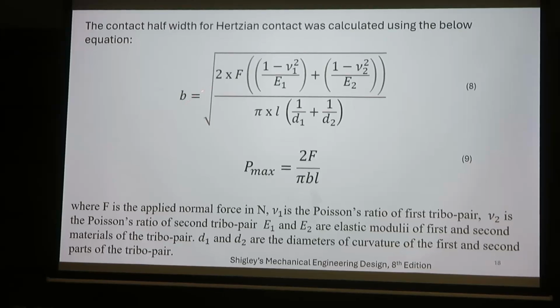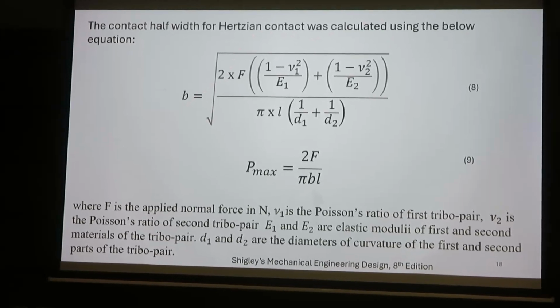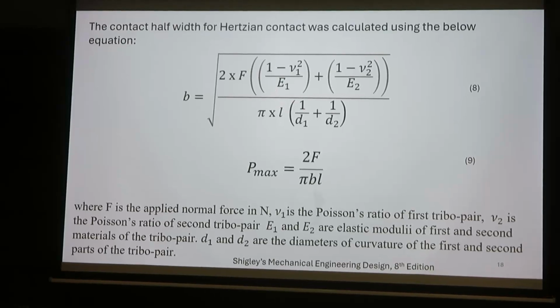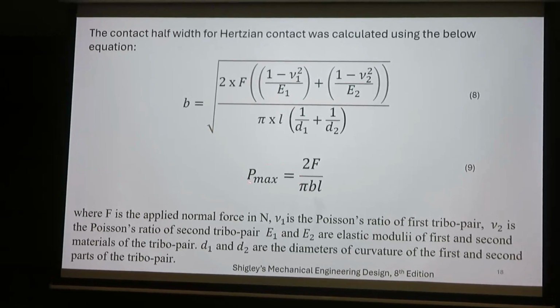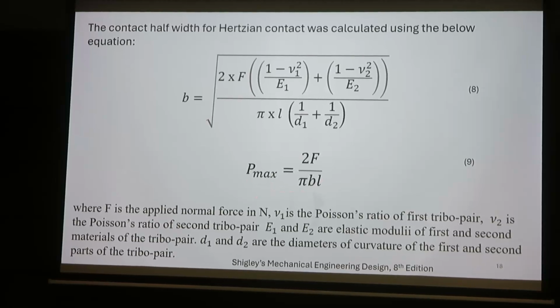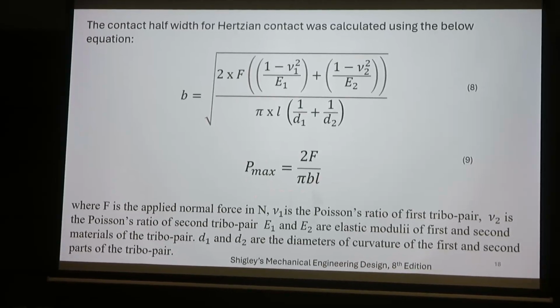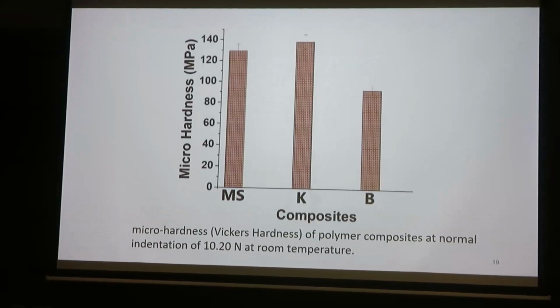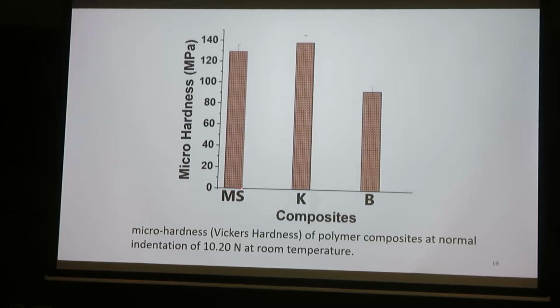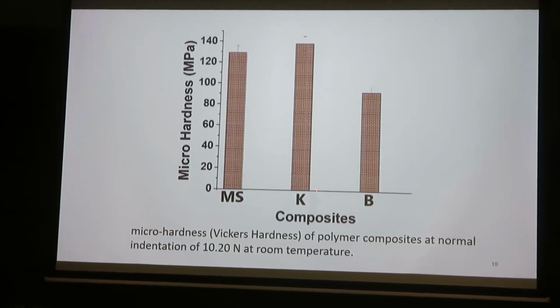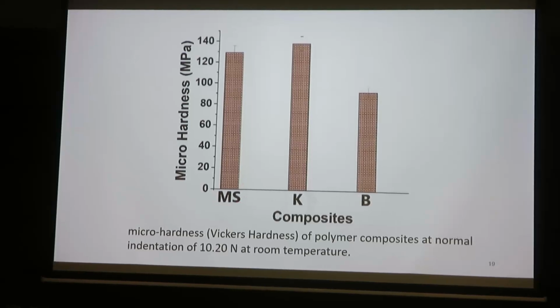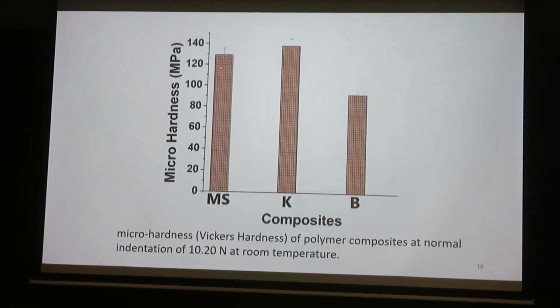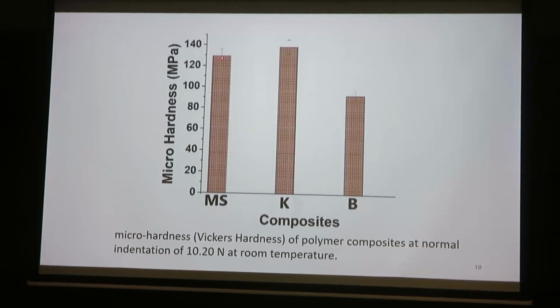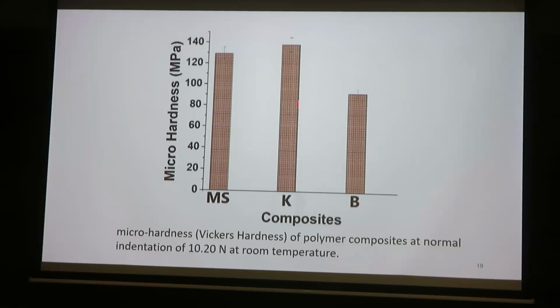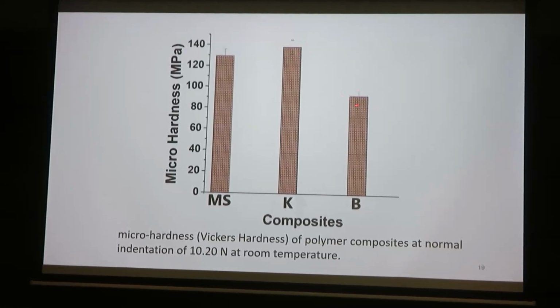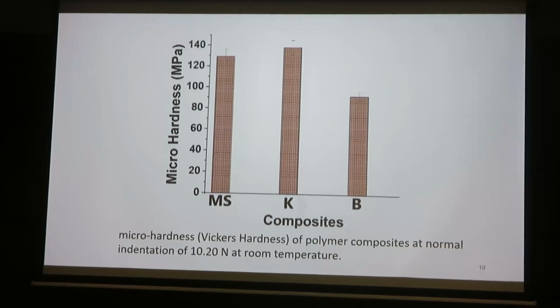The contact area was calculated using the Hertzian contact. So since it is a line contact, we use this equation for line contact. And then we calculated the pressure. So this is not the nominal contact area, this is the Hertzian contact area. So micro hardness, for example, the first one where we do not have Kevlar, so this is MoS2 and UHMWPE. So hardness is in this range, about 130 megapascal. With Kevlar, there is a slight improvement, but with base oil, the hardness goes down.